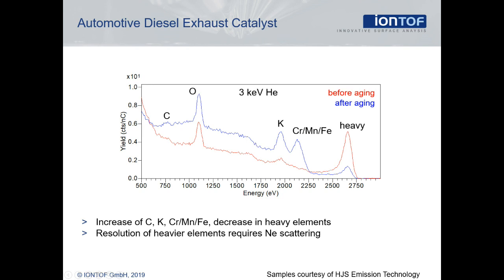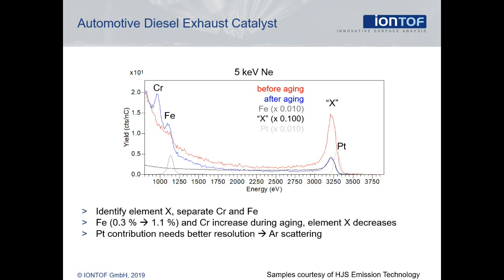For better mass resolution, 5 keV neon scattering is required. By using 5 keV neon scattering, the metals can now be resolved, and it turns out that manganese is actually not present, but chrome appears during the aging and iron strongly increases to about 1% surface coverage. For the heavy elements, the identification and quantification of element X, which remains confidential at this time, in the untreated catalyst is possible.